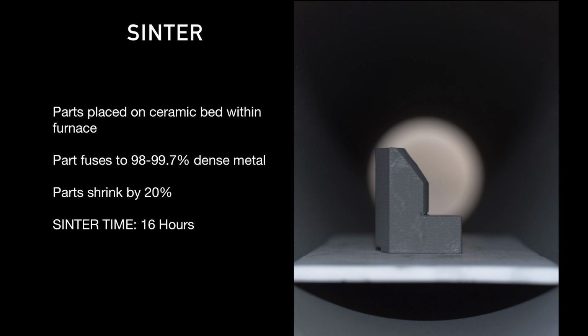99.7% dense metal. The sintering time is about 16 hours, and that includes the time from placing the part and hitting start until the part is cooled down and is ready to remove from the furnace. You can fit multiple parts inside of the furnace, so depending on which furnace you pick, the Sinter 1 or the Sinter 2, we have larger or smaller sintering areas. So you can put as many parts as you can fit inside of that area for each sintering run.